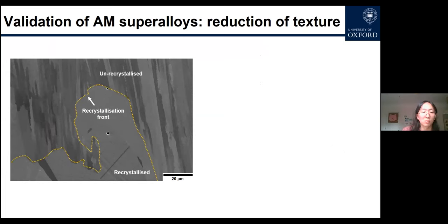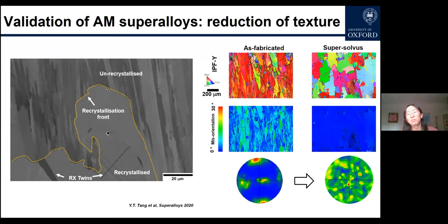Different things we have also tried to achieve was to remove the anisotropy of the material. As we have mentioned, just like single crystal, the 100 orientation is the preferred orientation when it is aligned with the heat flux, and this is usually produced in anisotropic superalloy by additive manufacturing. If you heat treat it at high enough temperatures, you can possibly trigger recrystallization because of the inherent high density of GNDs. And then you can end up with a much less textured material by the promotion of that.